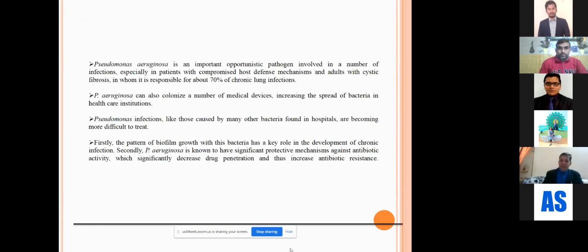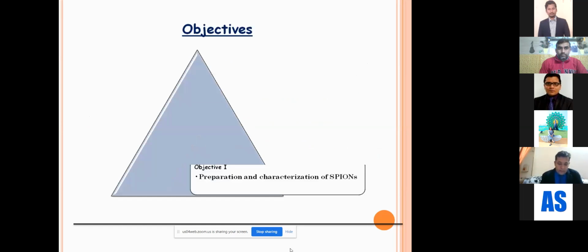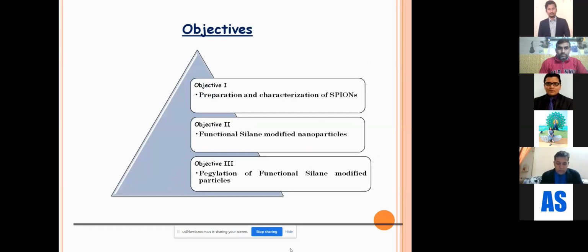we could see is one of the most pathogenic infections, where they make the patient immunocompromised and cause a lot of infection, particularly in the lung system. And that is why the work was more or less focused on Pseudomonas aeruginosa. And there we have done three things. First, how we need to prepare and characterize the superparamagnetic iron oxide nanoparticle, followed by functionalization with silane modified nanoparticles, and pegylation of the functionalized silane modified nanoparticles.